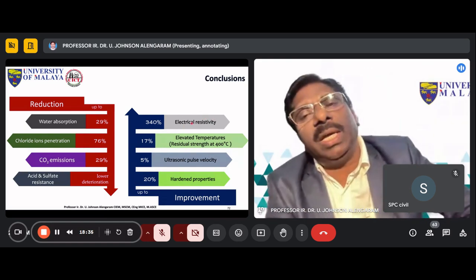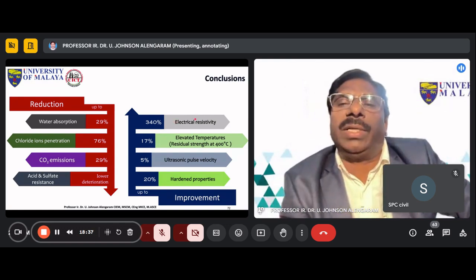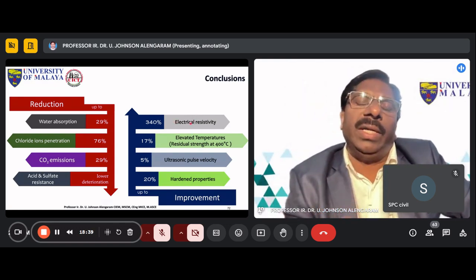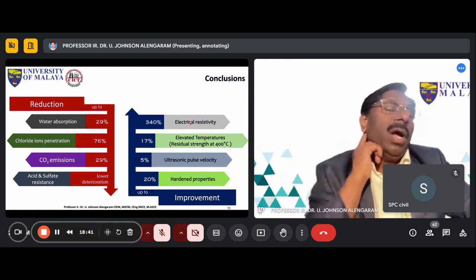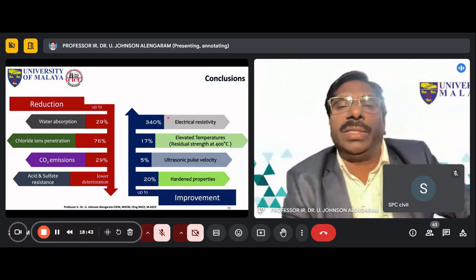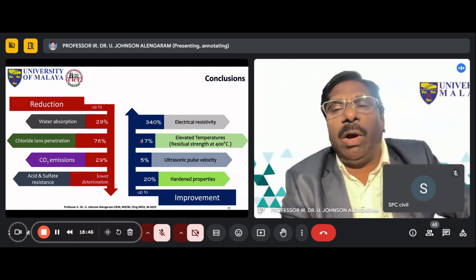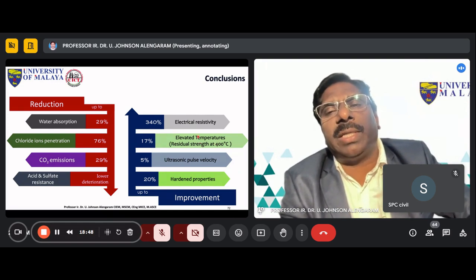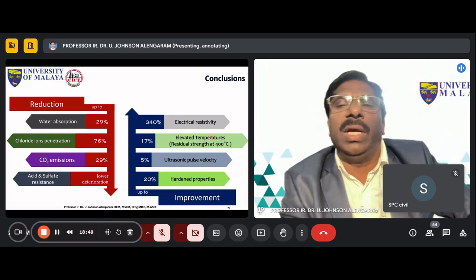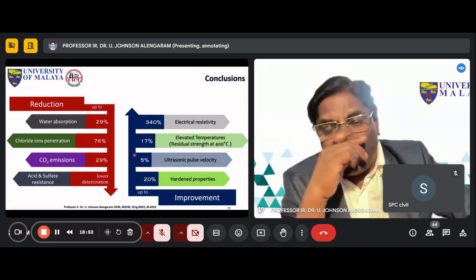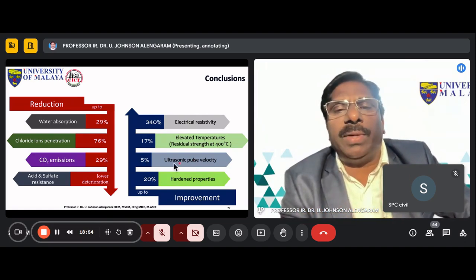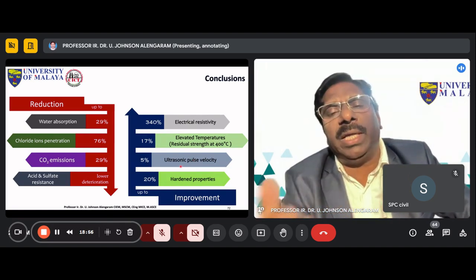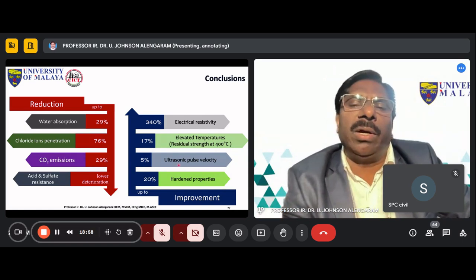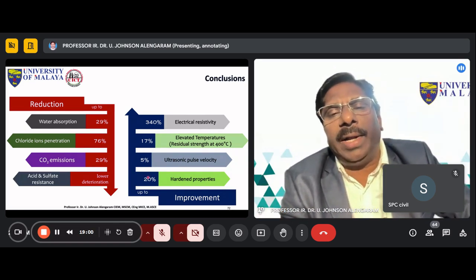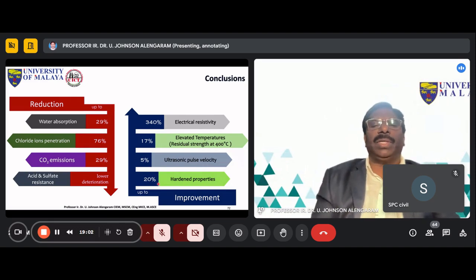Also, on the positive side, electrical resistivity is used to measure the corrosion. If supposing there is a steel inside, we can measure the electrical resistivity. That directly or indirectly gives you corrosion resistance. Thereby, it is improving 340%. We also tested the residual strength at a temperature of 400 degrees Celsius. The residual strength was 17% higher. The ultrasonic velocity, which indicates the uniformity of the concrete, is 5% higher. The hardened properties, generally, we got 20% improvement.